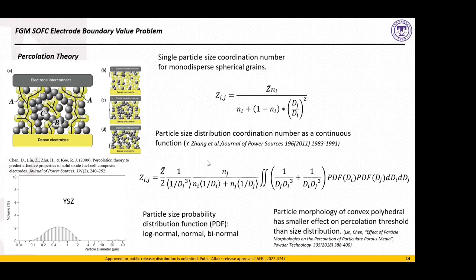So a single particle size coordination, this is for monodispersed spherical grains, is given by this relation. The coordination number just refers to the number of particles that a given particle is in contact with, which will tell us whether or not it's able to form a conductive path. Now, Zhang in Journal of Power Sources laid out this generic integral formulation here for particle size for coordination numbers with a probability size distribution to the grains.